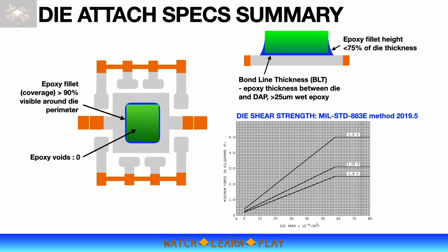Epoxy voids under the die must be 0. Voids can lead to thermomechanical stress that can damage the die. Bond line thickness needs to be at least 25 microns with wet epoxy. But note that too high BLT might cause unnecessary die rotation issue.